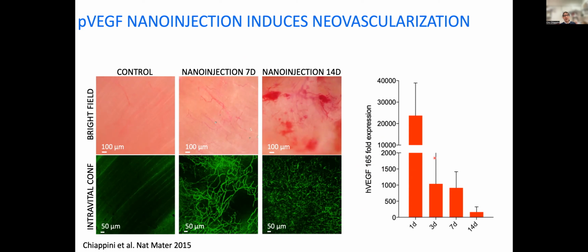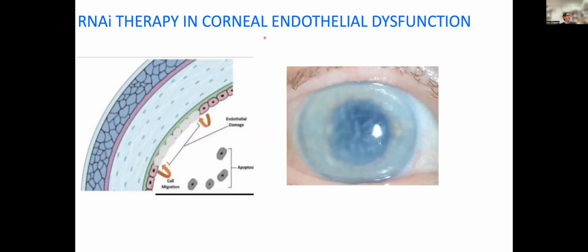But since then, we've moved into using this approach of delivering nucleic acid topically to tissue to address specific diseases. And one of them is corneal endothelial dysfunction. What happens in corneal endothelial dysfunction is that you lose the cells that die off on the inside of your cornea. And these cells don't regenerate because they are senescent, and they can't reproduce themselves anymore. And when you lose them, you can't control the ingress of water and fluids within your cornea. The cornea swells and you lose clarity and you lose vision.